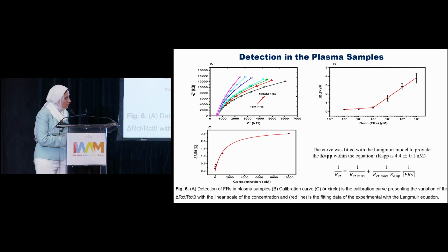We continued measuring the calibration curve, but here we generated our calibration curve against the concentration only, not logarithmic, using the Langmuir equation model to obtain the apparent affinity constant between folic acid and folate receptor. It was around 4.4, nearly the same value obtained from a previous study.